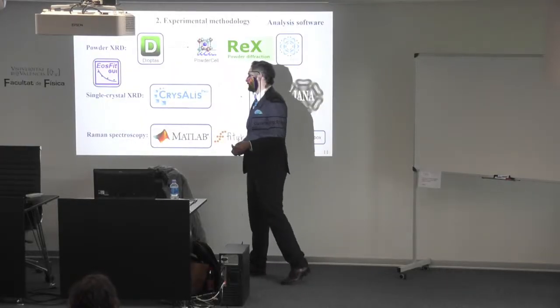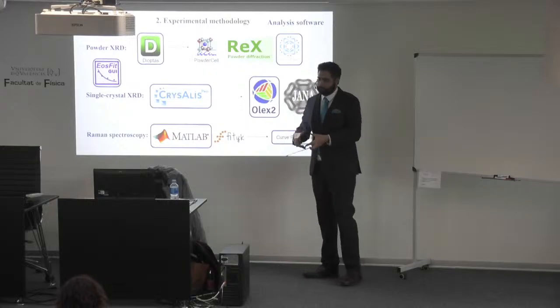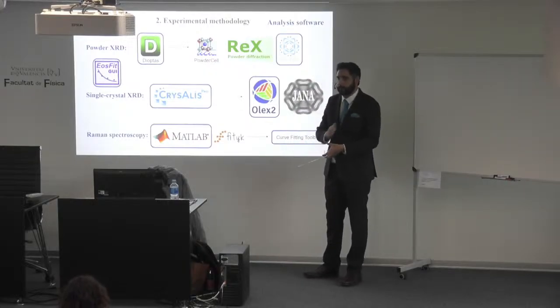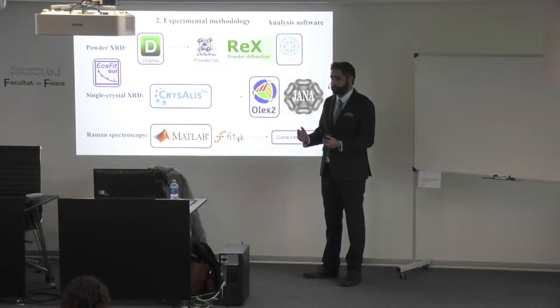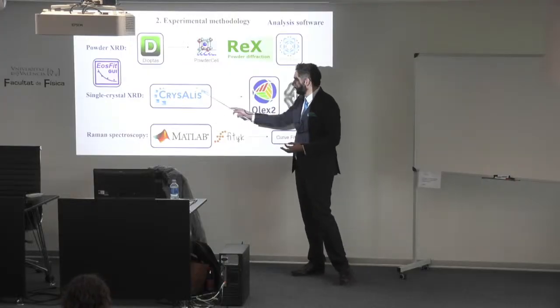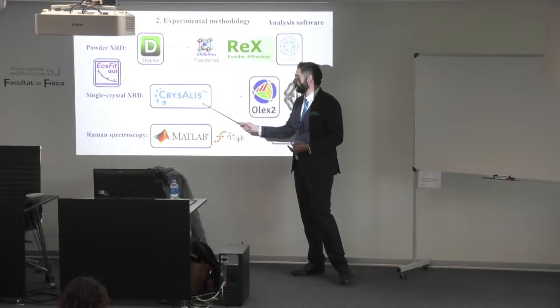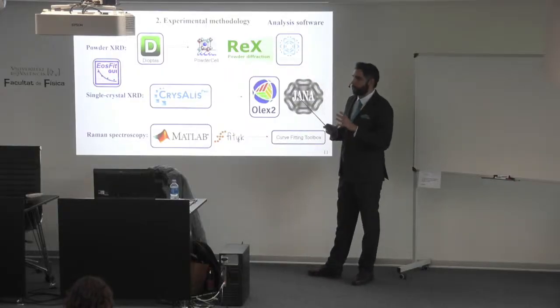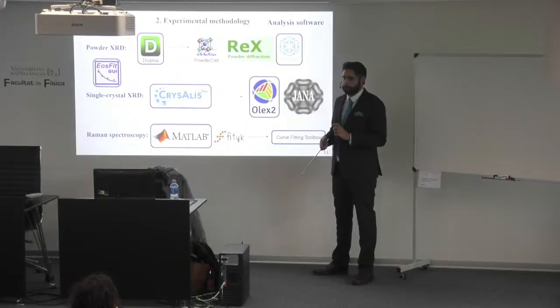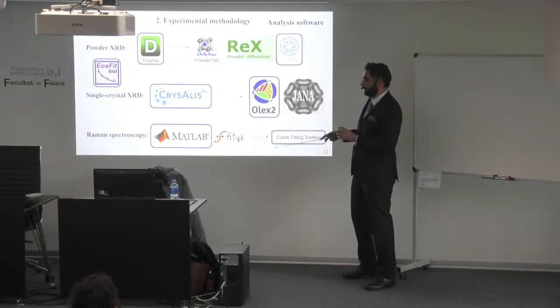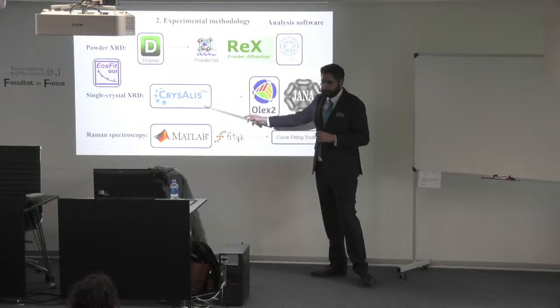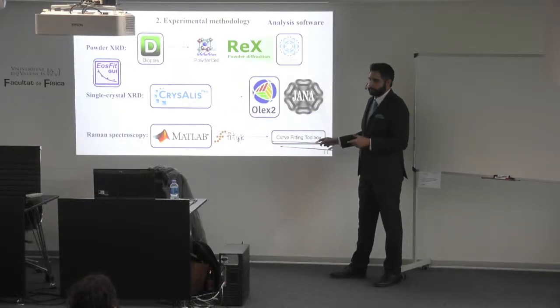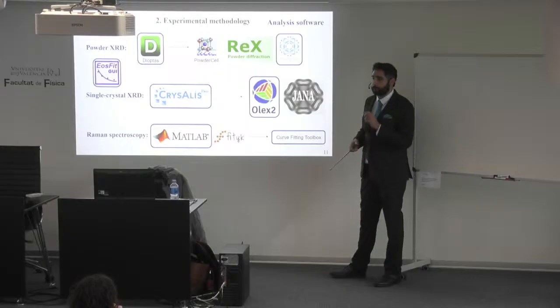Then, if we use single crystal, there is not just one diffraction image. We have a lot of them. In my case, 128. So I have to process all of them, in this case with CrysAlis, and recognize the most repeated reciprocal space, or the structure that is most fitting the most peaks, and reduce it in order to check that it is the correct one. When we resolve the lattice parameters with CrysAlis, then we can feed this information to OLEX2 in order to find the atom positions.